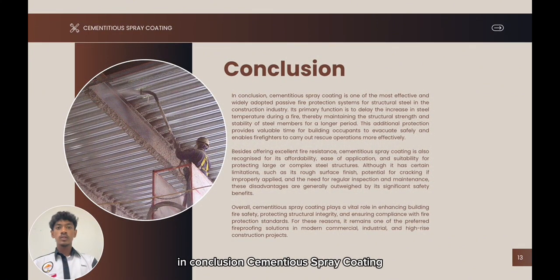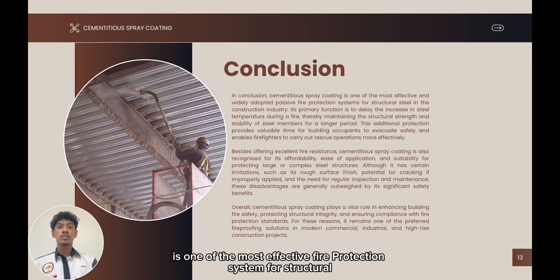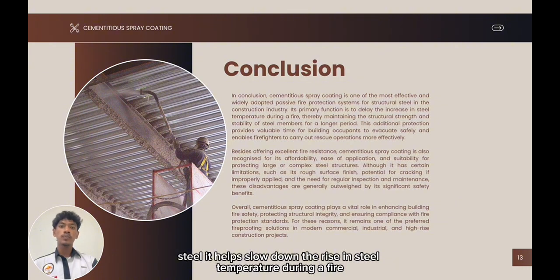In conclusion, cementitious spray coating is one of the most effective fire protection systems for structural steel. It helps slow down the rise in steel temperature during a fire, allowing the steel to remain strong for a longer time. This gives people more time to evacuate safely and helps firefighters to carry out rescue operations.